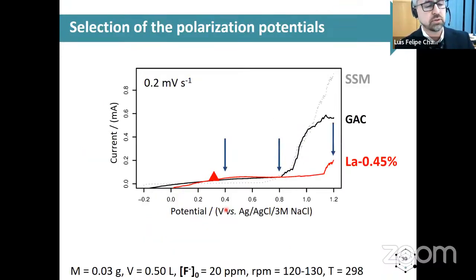Because of the results of the potential of zero charge, the selected half-cell potentials were 0.4 and 0.8, which are above the highest potential of zero charge for the material impregnated with lanthanum at 0.45%. At values higher than 0.8, you can see that the oxidation of the material, especially the pristine one, is much higher. The interesting thing is that the lanthanum protects the material from oxidation, because here the oxidation starts at much higher potentials.